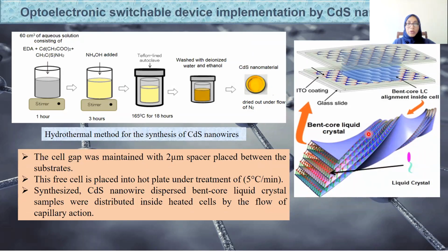Now let's have a look into the optoelectronic switchable device implementation by CdS nanowire liquid crystal composite. This figure shows the fabrication of CdS nanowire. CdS nanowire is fabricated using hydrothermal synthesis, where an aqueous solution of ethylenediamine, cadmium acetate and thioacetamide was prepared and it was left for 1 hour with continuous uniform stirring by a magnetic stirrer. Then 100 ml of ammonia solution was added, which turned the solution dark yellow.